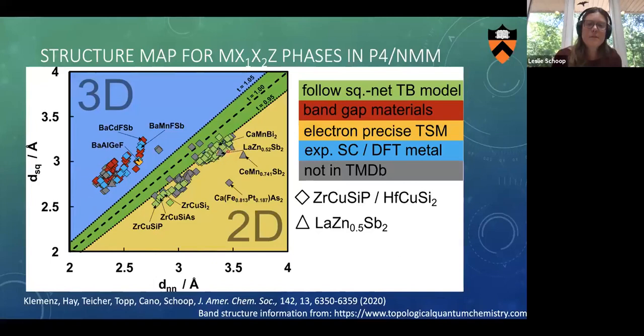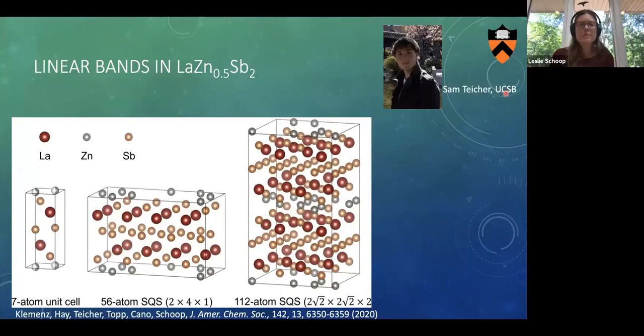And so we picked out one of them, lanthanum zinc 0.5 antimony, to understand if our method actually makes sense and predicts these band structure motifs correctly. There's a good reason this material is not in a database, because it's off-stoichiometric, and DFT becomes much more complicated to run. If you want to establish a database of 20,000 or 100,000 materials, I don't know how many they did, it's a massive amount of time and materials, you need to make your cut somewhere, and it's a very sensible cut to not look at off-stoichiometric materials. However, that gave us the chance to check if we accurately predict this to be a topological semi-metal. And so we did this in collaboration with Sam Teicher from UC Santa Barbara.